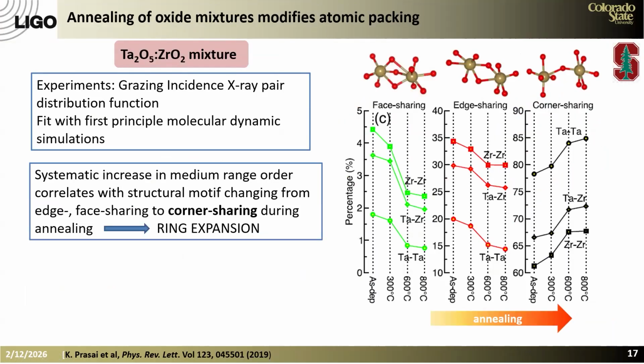There are other studies that have been conducted in mixed oxides with the goal to try to understand how we can make better coatings for gravitational wave detectors. And what I show here is work that was conducted by our colleagues at Stanford that showed that when we anneal materials, essentially this is grazing incidence pair distribution function measurements. These are done at the synchrotron.